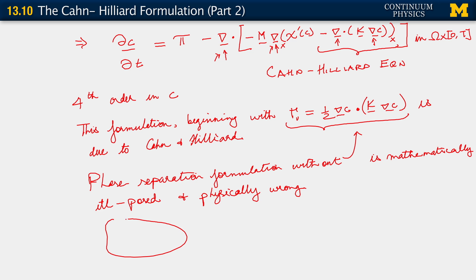Penalizes the development of that interface and thereby gives us a unique solution for the formation of the interface. So what the Cahn-Hilliard problem does, the Cahn-Hilliard formulation does, is to say that it penalizes the formation of that interface. And it penalizes the formation of that interface by saying that if you are going to develop these gradients in concentration that we have decided to denote with our contours of concentration changing from alpha, from concentration of C alpha to a concentration of C beta, so it says that if you're going to develop this concentration gradient, you're going to pay a price for it.